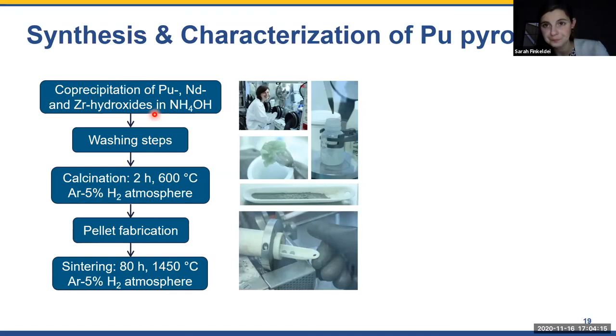So what I did is I started by precipitating neodymium and zirconium hydroxides, and then added the plutonium later on, and in the end, I was able to acidify the neodymium nitrate and zirconium oxide chloride solutions enough to add the plutonium and then really co-precipitate. Because the beauty of wet chemical approaches is that you are in theory capable of a homogeneous precursor at the atomic level.